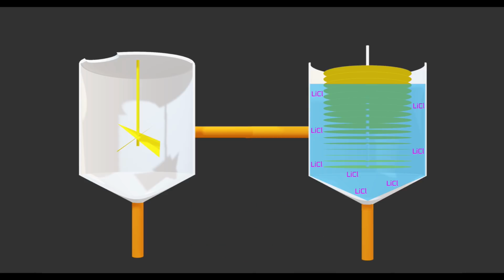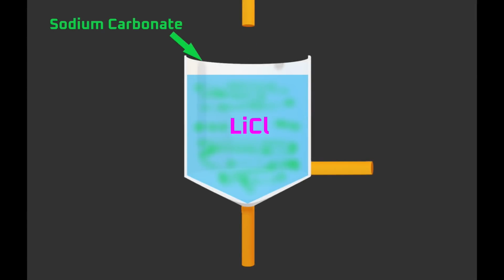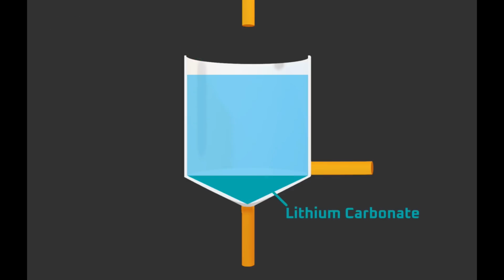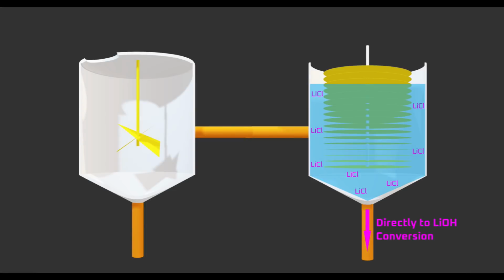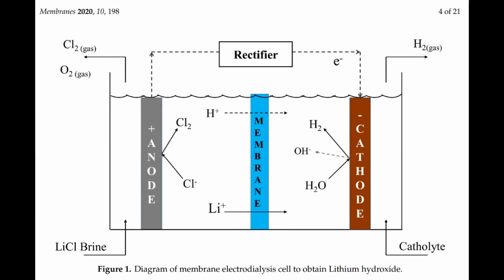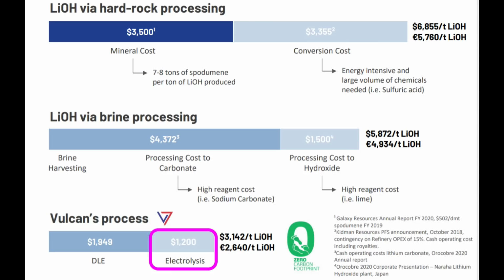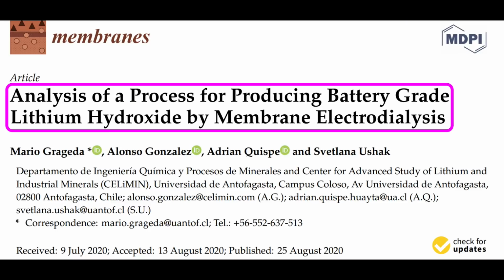As for the lithium chloride solution, in this process, the extraction would stop at DLE and there would be no chemical extraction step to precipitate the lithium chloride from solution as lithium carbonate. The lithium chloride would be piped directly to another process for the next step, which is conversion to lithium hydroxide by membrane electrodialysis. Membrane electrolysis appears to be what Vulcan Energy is doing in Europe, and from the few papers I've found on the topic, it seems feasible.